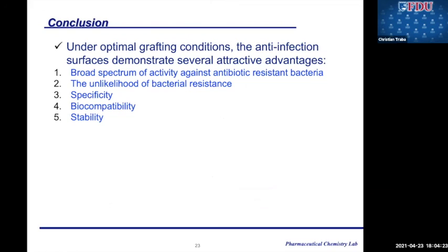Acrylic acid grafted surfaces were constructed as a platform for the immobilization of silver nanoparticles in our study. When generated under appropriate experimental conditions, silver nanoparticles were cross-linked and formed cross-linked nanocoatings and could kill bacteria indiscriminately at the site of adherence without releasing silver nanoparticles.